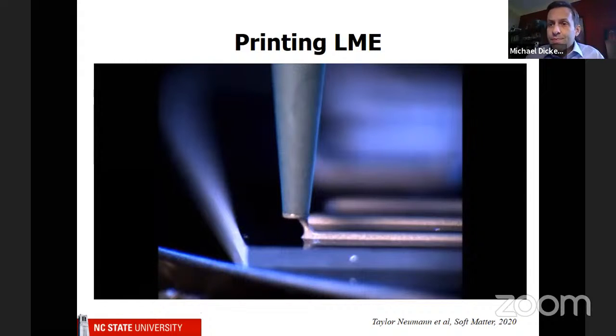So there's, I guess, 3 parts to this answer. The first is if you take one of these wires, which remember are about the size of a human hair, so they're very small, in our experience, you can run literally amps of current through it without any problem. And so the short answer is nothing happens. It's kind of boring. But obviously, if you run enough current through it, they will start to get warm and you can get joule heating. They're not going to get really hot. In the experiments I've shown you, they go up to maybe 40 degrees Celsius or something. So it's not enough to burn you, but that requires a lot of current.